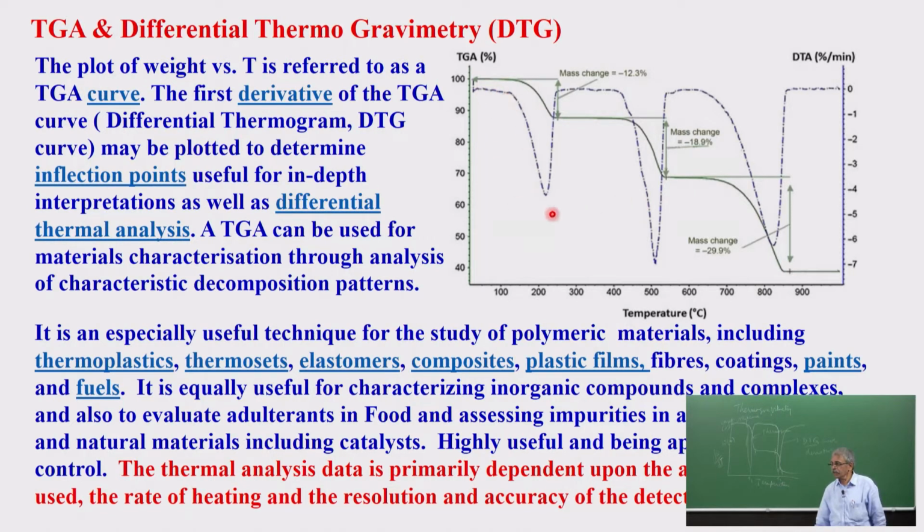So, this dashed curve is the derivative. You can see that looks very nice, one. Therefore, there is only one, but when you look here, there is one small turning point, another small turning point and a main peak. At those points some processes are going on, different kinds of losses, and then here nothing is there, and then when you come again here, you can get the temperature here. That will be the temperature for that process, whatever small reaction is occurring, you can take that temperature.